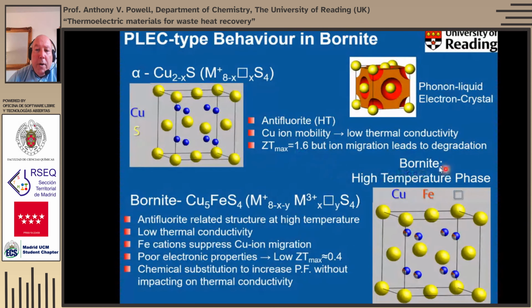So we looked at this material bornite, which is a high temperature phase, is also anti-fluorite related. The difference now, this would be the end member here without any copper deficiency would be M8S4. This is M6S4. So that means there are 2 vacancies per formula unit, and those are distributed at a high temperature. The vacancies, the copper and the iron are distributed randomly over tetrahedral sites in the anti-fluorite type structure at high temperatures. It has a low thermal conductivity, and in principle, we think that the Fe cations are going to suppress that copper ion migration, but unfortunately, the electronic properties are low, and we get a ZT of only 0.4. So we're going to look at chemical substitution to increase the power factor without impacting on that low thermal conductivity.